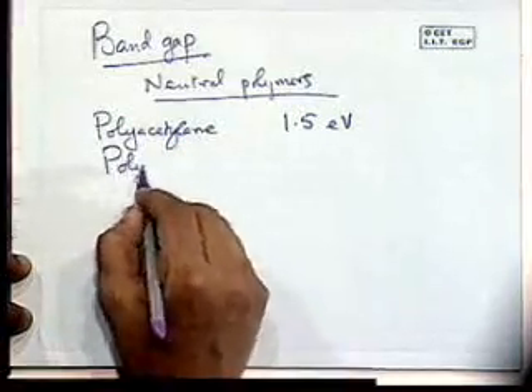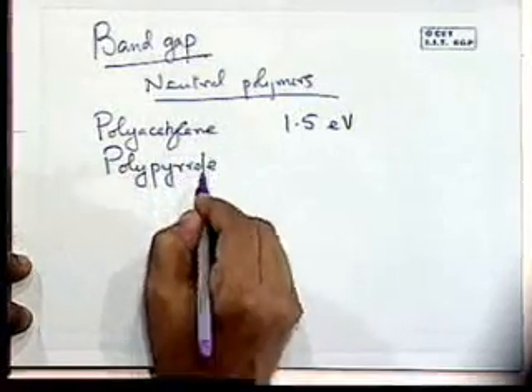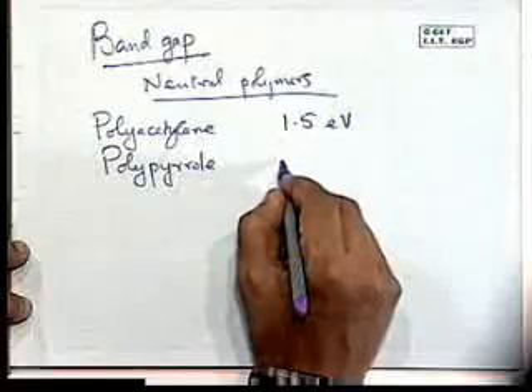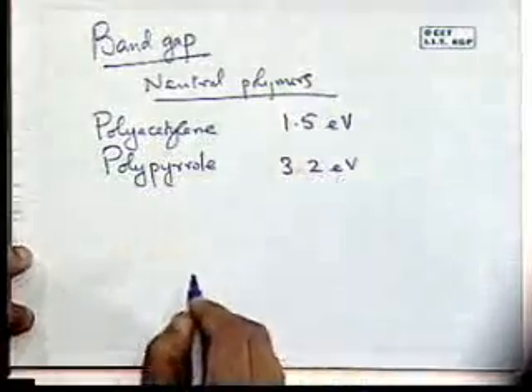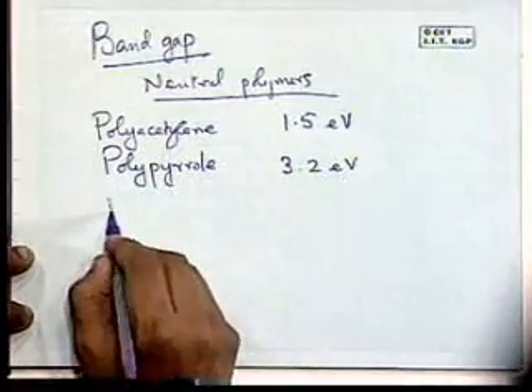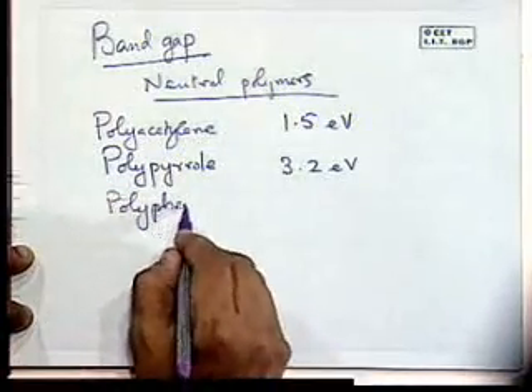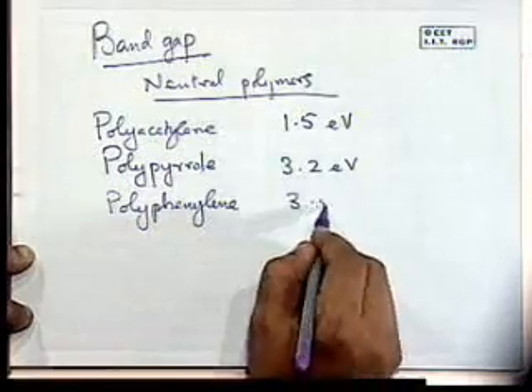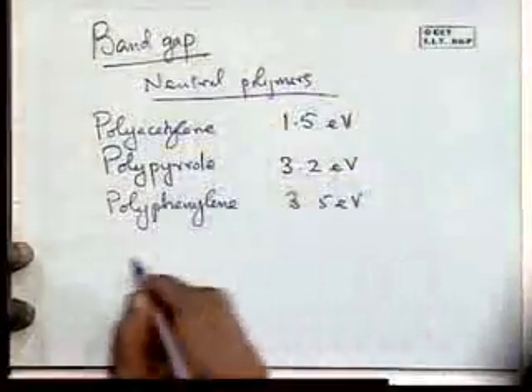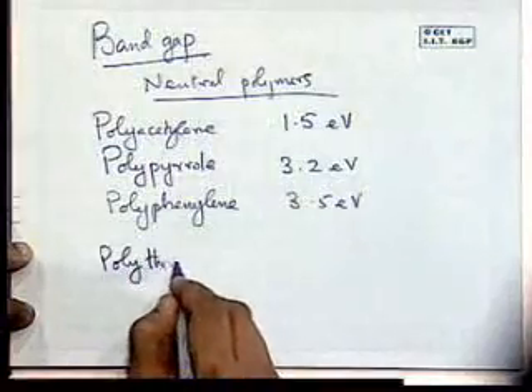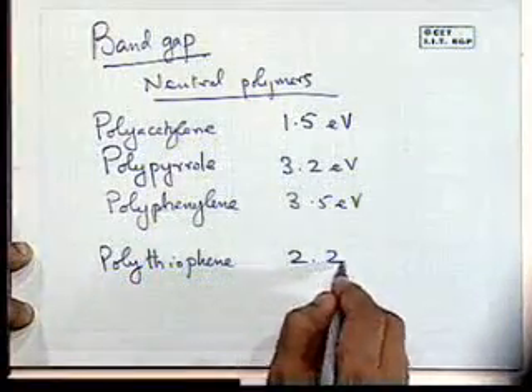Then there's one called polypyrrole, which is the other class we spoke about, the heteroaromatic group, which has got something like 3.2 eV. Polyphenylene, or phenylene, 3.5 eV. Here we are into the UV. This is in the infrared, and this is in the UV. And in between also there's stuff with polythiophene, 2.2 eV, and so on. And some of these can be tailored, putting in different groups into it. You can tailor it. That's the beauty of the polymers. You can adjust it to what you want.